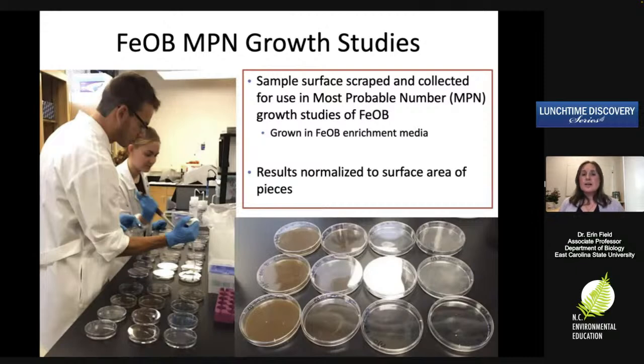So we took those shipwreck pieces that I told you about, those samples we collected in the scraped off material, and we set up what we call a most probable number study, an MPN. And so we can grow them in the lab. And that's what you're seeing both Cody and Kyra do here. So you start by inoculating it in this media. This media is specifically made to grow iron oxidizing bacteria. We do a serial dilution in order to get a relative abundance of how many may be there. And then we normalize to the surface area of the shipwreck pieces so we can compare across the board.